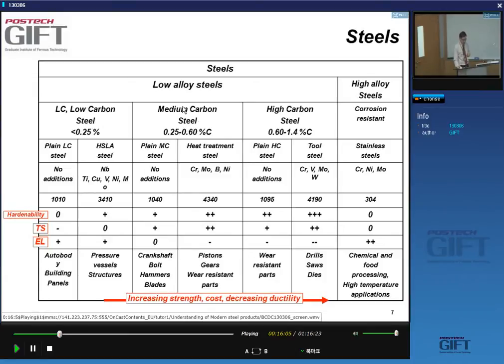Same with the medium carbon steels, 0.25 to 0.6% carbon. You have plain medium carbon steels without alloy additions, where the properties are basically achieved by carbon, and versions of these steels which are alloyed with elements which will allow you to perform thermal treatments on them. And we'll discuss these. Okay. So what we see is that if you go from low carbon steel, medium carbon steel, to high carbon steel, what you typically have are materials which display an increasing level of strength and hardness, cost, because of the alloying, and also a decreasing ductility.